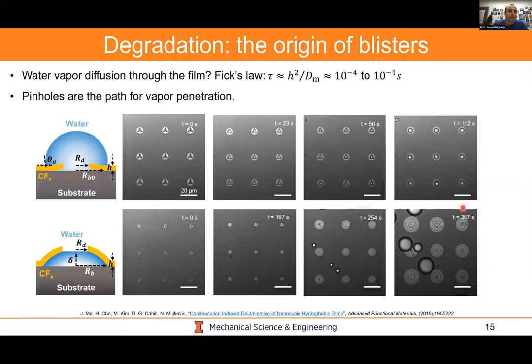So if we were to look at two different cases, in this case, two very different defect geometries and sizes, both geometries are triangular, but very different sizes. You could see on top here, we have large defects, and on the bottom here, we have small defects. What you're actually seeing is as you condense on these, if the defects are quite large, you'll actually get water forming within the defect, but not delaminating the substrate or the coating itself from the substrate. If you actually have very, very small defects, you'll actually have the blister fill and you'll have delamination occur. And these are actually interference fringes because we have an optical filter. And so it's telling us that there's something about the size of these defects inside the coating, which is governing whether delamination of the coating occurs. This is very important.